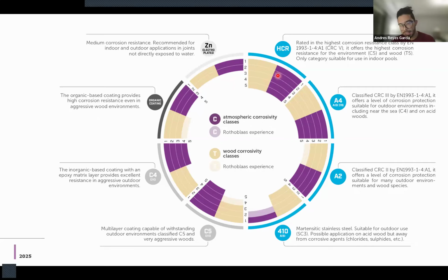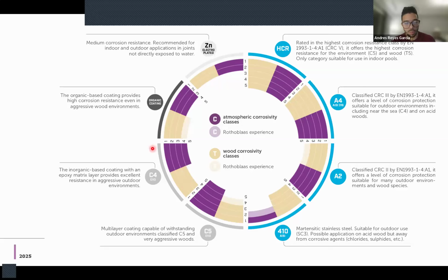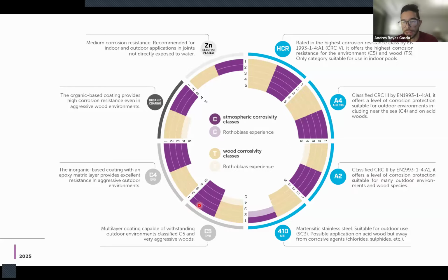So there are different stainless steels that go from martensitic 410 to HCR. There are also many coating types for the carbon steel, from zinc plated to different proprietary coatings like organic coatings, C4, C5, Evo coatings like Rothoblaas does. But depending on the corrosion protection that your project needs, and the uncertainties that you might have on the job site, you can choose a different corrosion protection to lower the risk on the construction site.